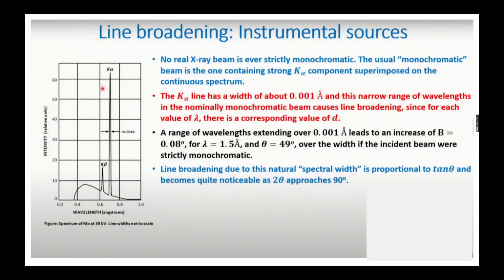So line broadening, the first thing is your instrumental source. No real X-ray beam is ever strictly monochromatic. The usual monochromatic beam is one containing a strong K alpha component, superimposed on the continuous spectrum. Line broadening is also due to the instrumental source, because the K alpha line has a width of 0.001 angstrom, and this narrow range of wavelength in the nominally monochromatic beam will cause line broadening, since for each value of lambda there is a corresponding value of d.